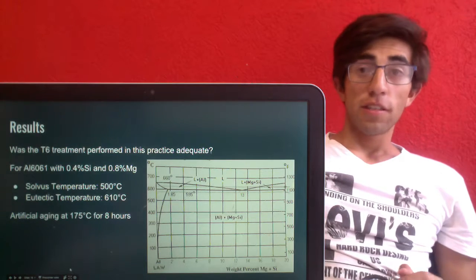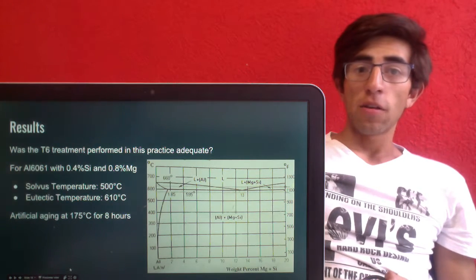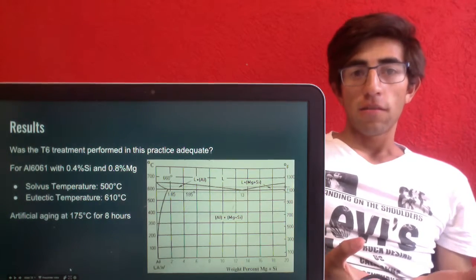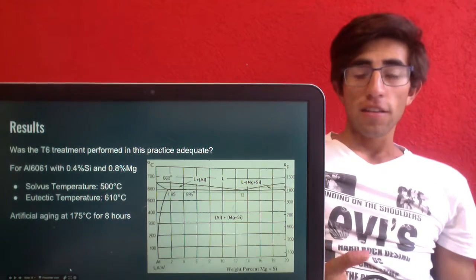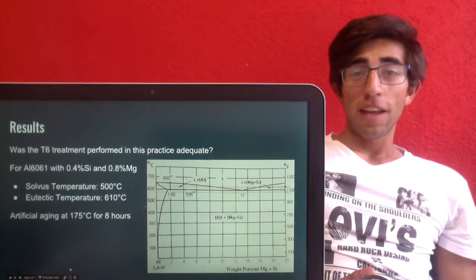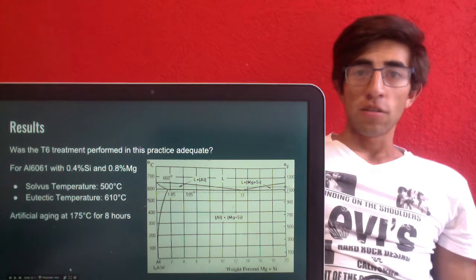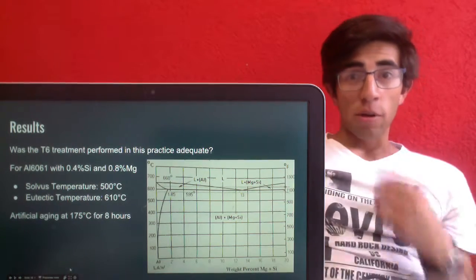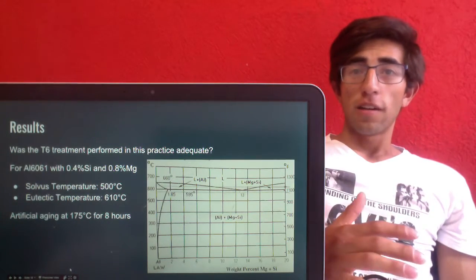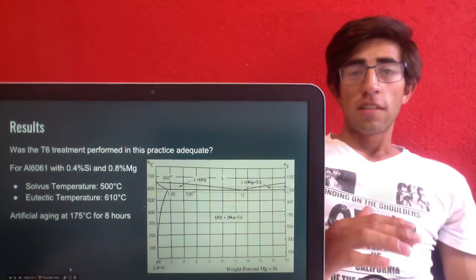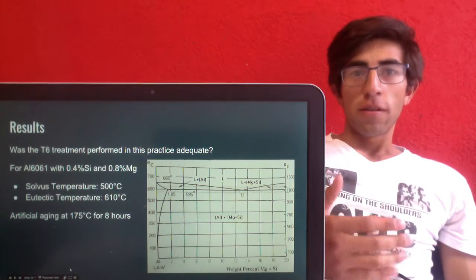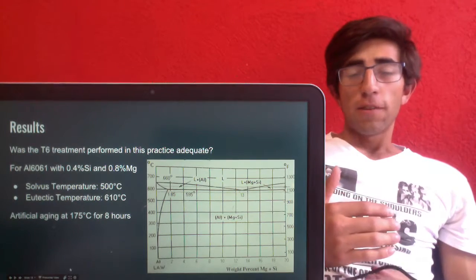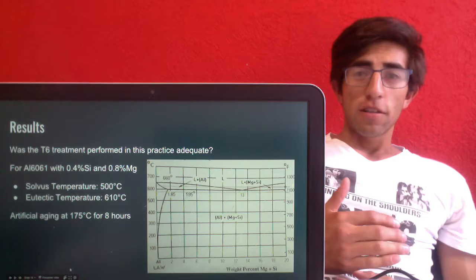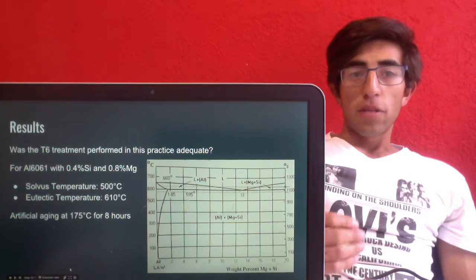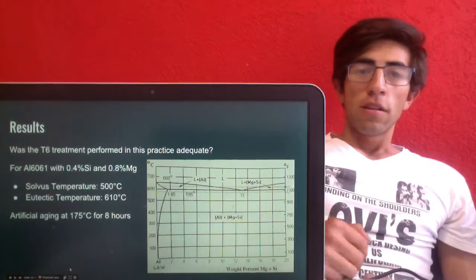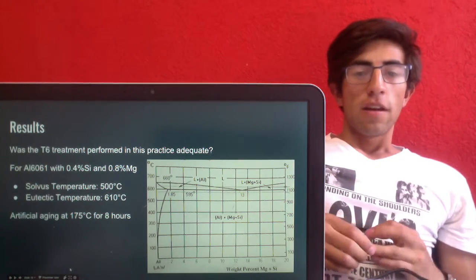So was the T6 treatment for this aluminum alloy adequate? Well, for the aluminum 6061, it has 0.4% of silicon and 0.8% of magnesium, and according to this table, the solvus temperature is around 500 degrees and the eutectic temperature is 610 degrees. So the solution treatment was adequate, and the artificial aging at 175 Celsius degrees for 8 hours for the best results, it's adequate. So yes, the treatment was performed adequately.